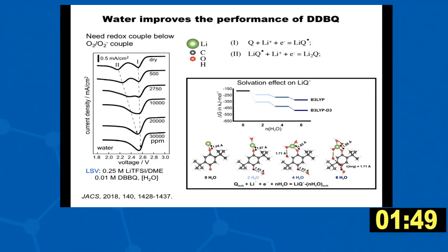So water increases the donor number of the solvent, but it also, interestingly, changes the potential at which these redox mediators work. And so this is the reaction, or the CV plot, of a dry DBBQ molecule. So this is the first reaction to form the first reduced molecule. This is the second one. And when you add water, what's interesting is the potential shifts closer to the voltage of the first reaction to form the superoxide, which is what you want. So this looks more promising to add water to these systems.